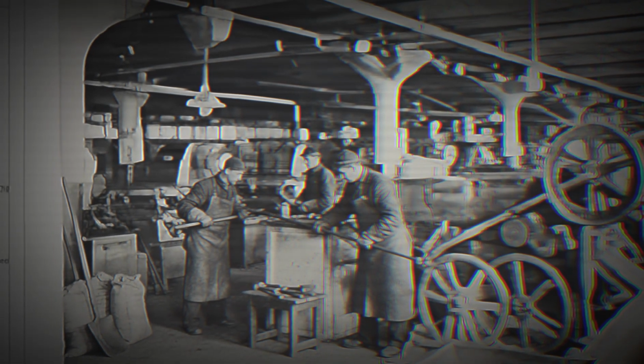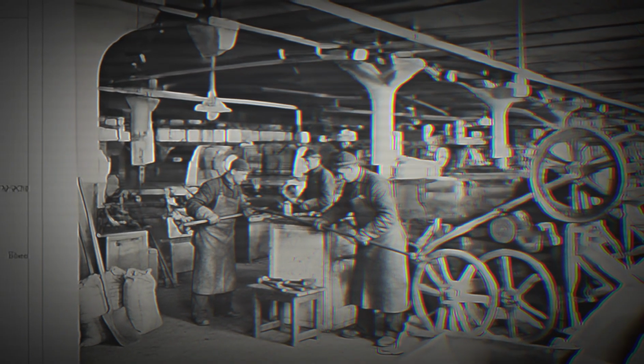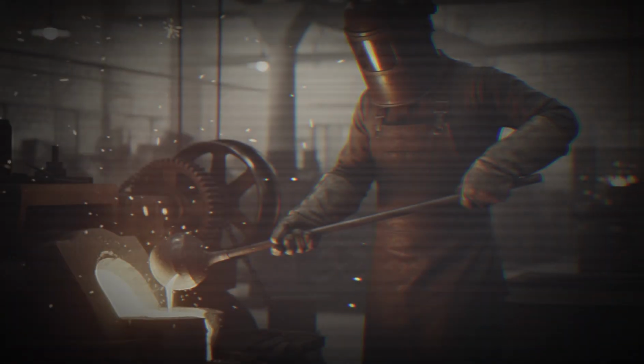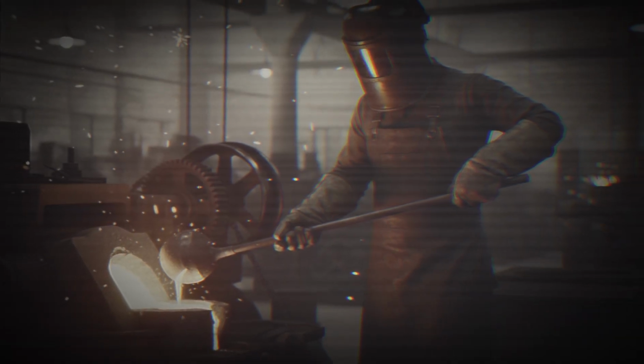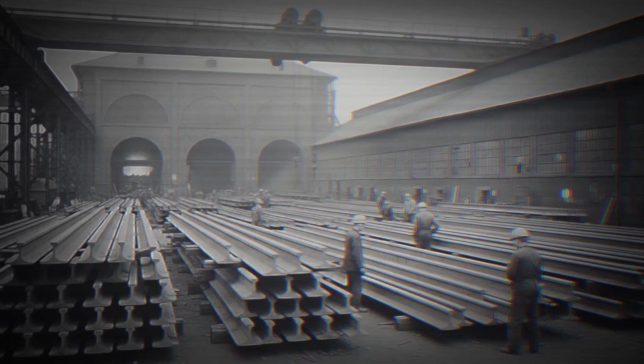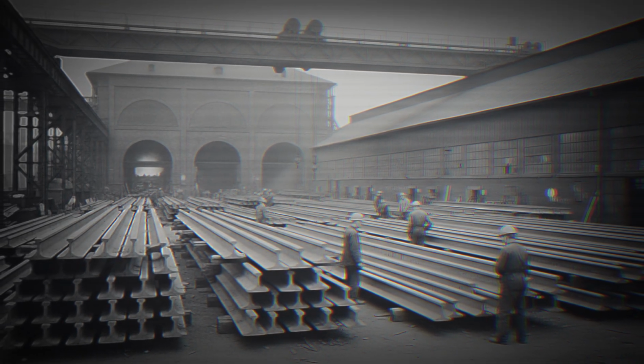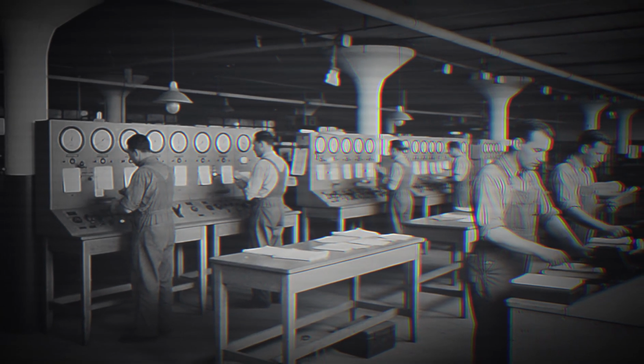Molten metal incidents. The most common serious injury category in open hearth operations was contact with molten steel or slag. Here's the physics. Liquid steel at 2,900 degrees Fahrenheit has a density of approximately 6.9 grams per cubic centimeter. It is heavier than water. When it contacts a cool surface, concrete, damp refractory brick, a thin metal floor plate, the result depends on what that surface contains. If the surface contains trapped moisture, water in concrete, wet sand, a crack in refractory brick that has allowed moisture infiltration, the liquid steel causes an instantaneous steam explosion.